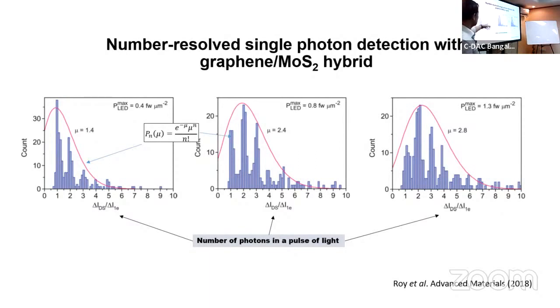We can actually look at the number of photons in a pulse of light, which follows the Poissonian distribution that I showed. And what is interesting about this is that as you increase the intensity of light, the modal value of the number of photons slowly shifts to higher and higher. So this is a single photon detection, single shot current measurement, which is different from the standard single photon detectors in silicon or superconducting nanowires.